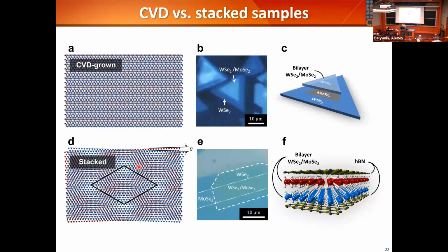So we've also tried to bring in comparison samples, this time grown by our friends who know chemistry. When they grow these two materials stacked together, because the lattice constants are so close, each layer deforms a little bit. Actually, in this material, there's no Moiré superlattice because each layer just stretches or compresses a little bit. Energetically, they tend to be perfectly aligned. Now we have a comparison between the same material without and with a Moiré superlattice. So this is also our way to check, are we insane? Are we just imagining things? Let's do some comparison experiments.